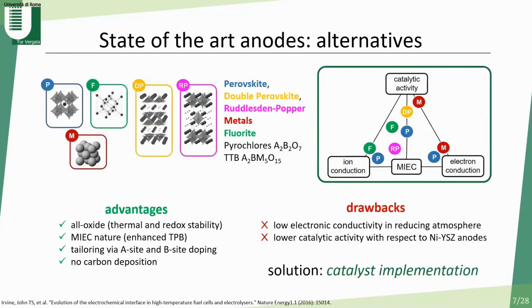Thus, how can we improve and overcome the problems of anodes? By using alternative anode materials, where the metallic nickel is removed or drastically reduced. Many metal oxides have been investigated so far, and here I report a list of their crystal structures. Among those materials, the most promising are the perovskite oxides, even though the main drawback is the reduced catalytic activity compared to nickel cermet. So most of the research effort has focused on catalyst improvement.